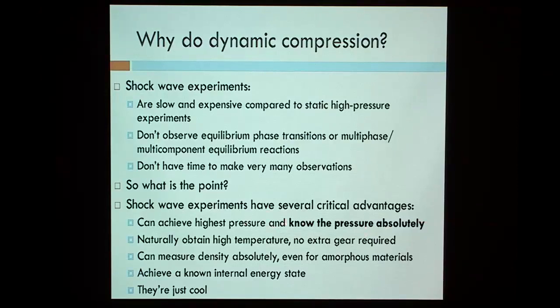The other key advantage of dynamic compression experiments is that we know the pressure as an absolute number from conservation of momentum. Whereas in every static high-pressure experiment that you can name, the pressure is a calibrated number that comes from some standard material. And the equation of state of that standard material has either been determined using a shockwave experiment, or at very low pressure, up to maybe 3 GPa, a gas pressure rig, where you can know gas pressures absolutely, or a density functional theory calculation. So almost all of our pressure standards are ultimately tied to shock compression experiments. And that's a key thing to keep in mind, even if you never do those shock compression experiments. If you think you know the pressure in your diamond cell, it's because somebody shocked your pressure standard.